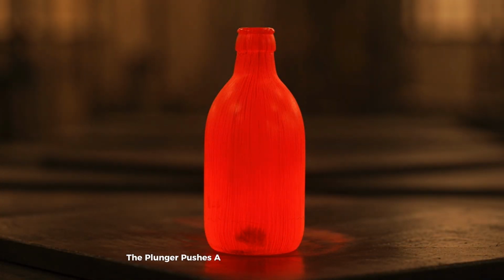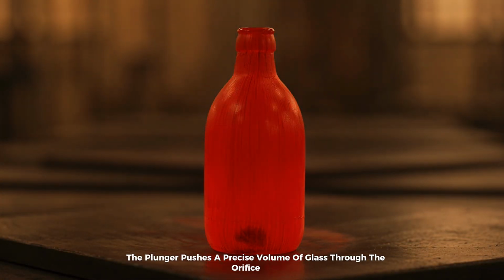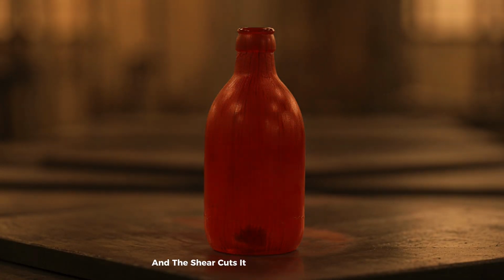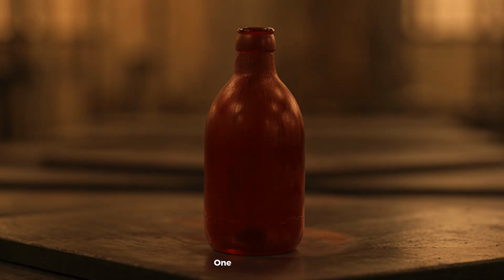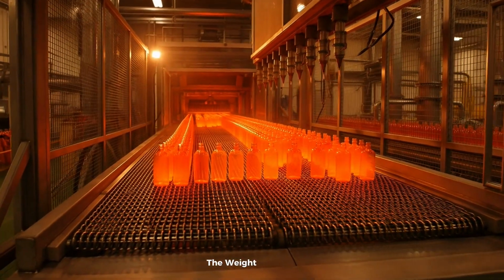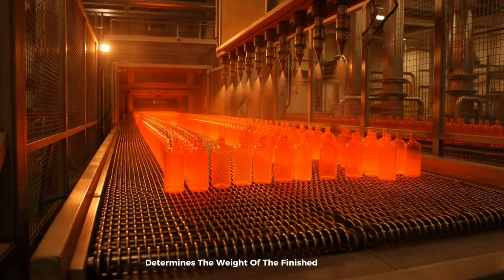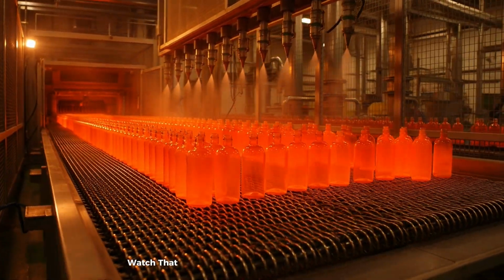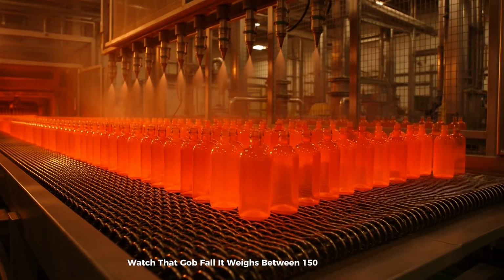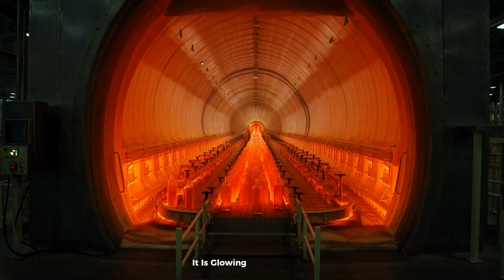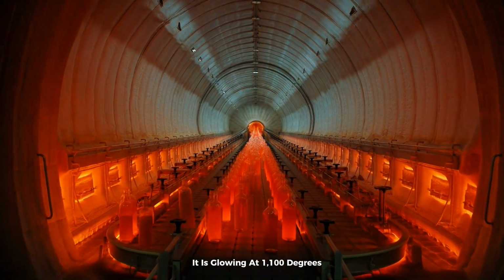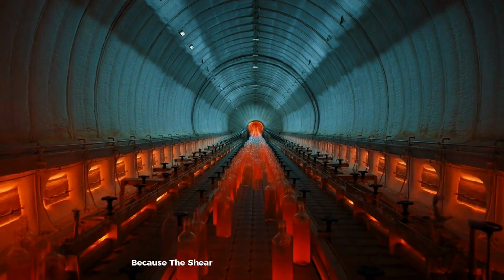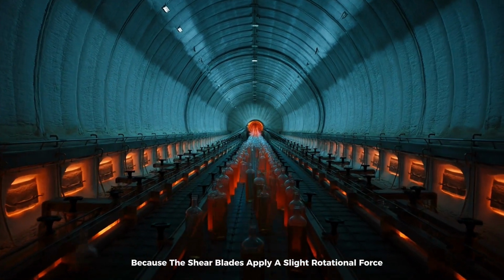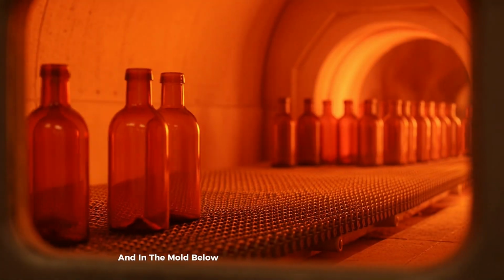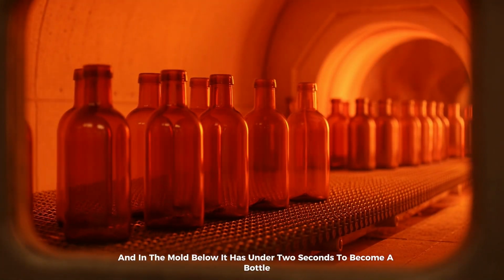The plunger pushes a precise volume of glass through the orifice ring, and the shear cuts it. What falls is called a gob. 1 gob. 1 bottle. The weight of the gob determines the weight of the finished bottle wall. Watch that gob fall. It weighs between 150 and 500 grams depending on the bottle being made. It is glowing at 1,100 degrees. It spins as it falls because the shear blades apply a slight rotational force. And in the mold below, it has under 2 seconds to become a bottle.